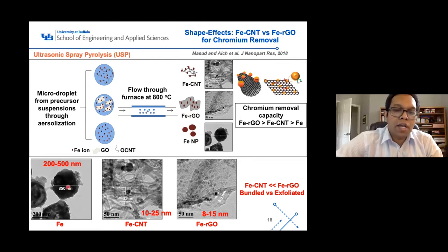So what we saw first in the size. If we don't have any support like carbon nanotube or graphene, the size of the iron nanoparticles goes to 200 to 500 nanometer, which is more than 100 nanometer. So they are not really in nanoscale. But when we have carbon nanotube, we can get iron nanoparticles as small as 10 to 25 nanometer. If you look at these string-like structures around this small iron nanoparticle, those are basically carbon nanotubes. On the other side, the graphene sheet is actually a single graphene sheet. It looks like a bed sheet, but it has a lot of 8 to 15 nanometer size iron nanoparticles.